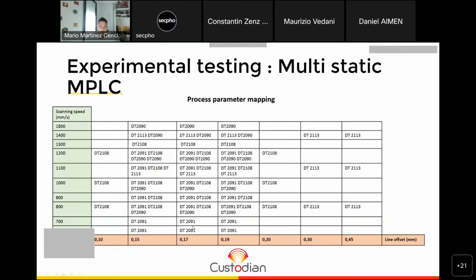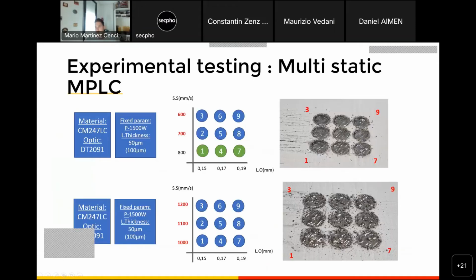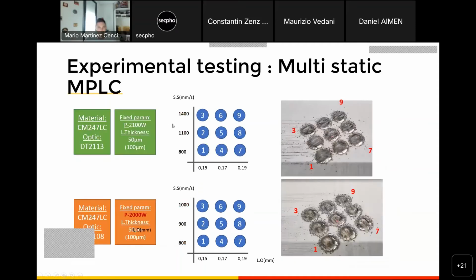This is the mapping that we did for the multistatic beam shaper. So for each optic, we tested different parameters. Konstantin showed before that each optic has an optimized laser power, and this was something that has been modified because we found plenty of problems during the development. And as you can see in these images, what we obtained was a very huge balling issue, especially in the contours of the parts. And of course, if we reduce the energy density, as you can see here, by increasing the scanning speed, we also get this balling issue in the hatch because there is not enough energy. So here I just wanted to show you some other experiments with different optics.